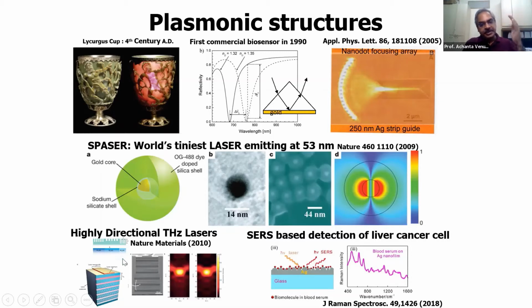So even from the semiconductor lasers point of view, the surface emitting lasers have been patterned so that you get nice collimated beams out, and then people also use it for biological or biomedical applications, including surface enhanced Raman, which is one good technique, where you just roughen your metal surface, and your Raman signals get amplified and enhanced because of the plasmon localized field enhancement.